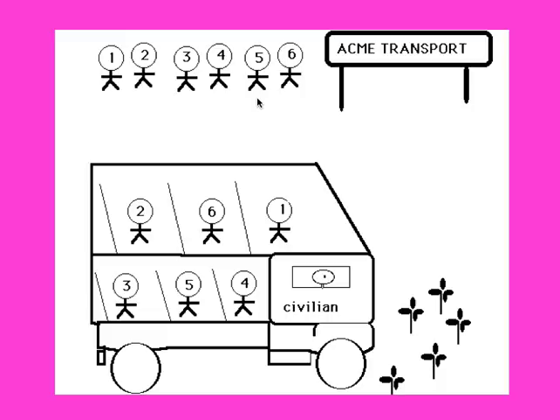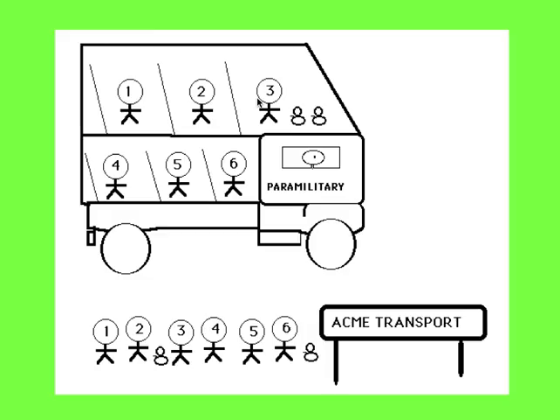There is a third possibility: you have both interstitial atoms and substitutional atoms, and the substitutional atoms are forced to go onto the bus in a disciplined manner, whereas the interstitial atoms do whatever they like and settle in positions which give the lowest free energy — for example, partition into the austenite. We call this a paramilitary transformation, and Widmanstätten ferrite is like that.